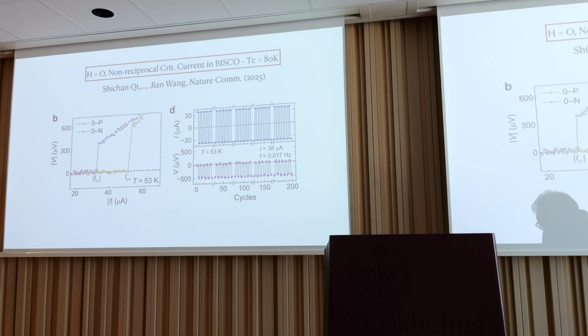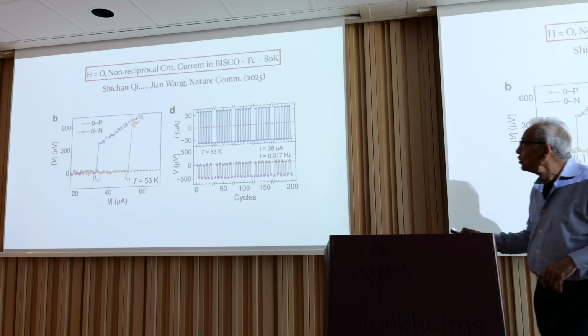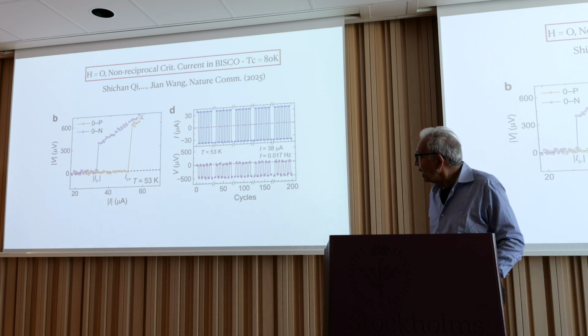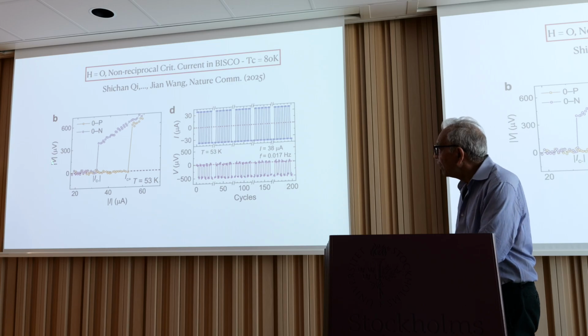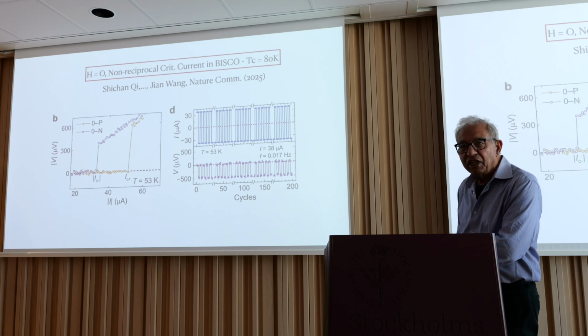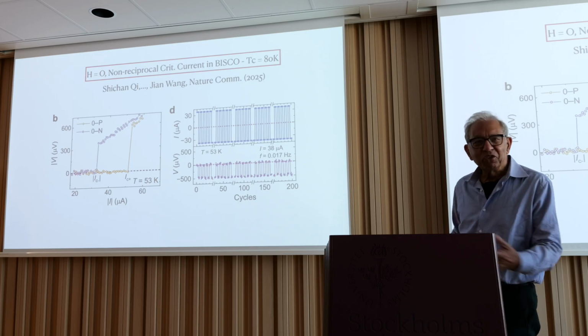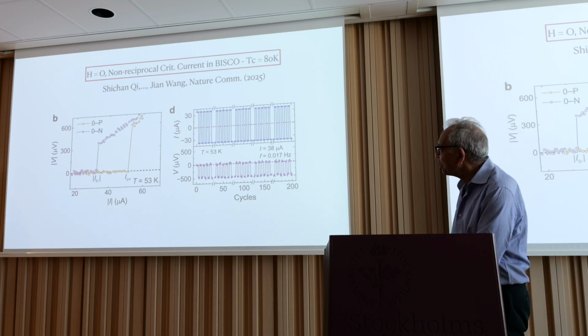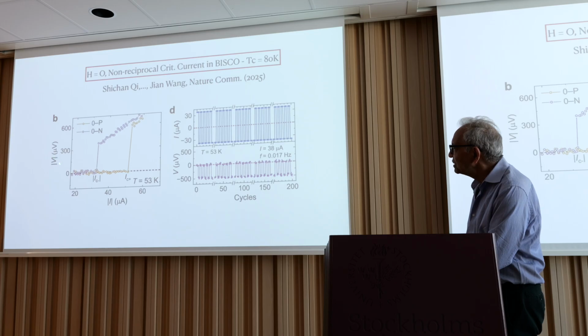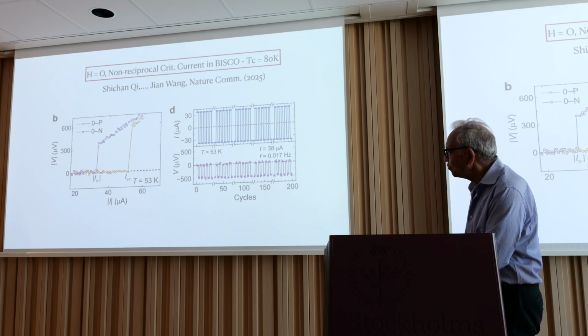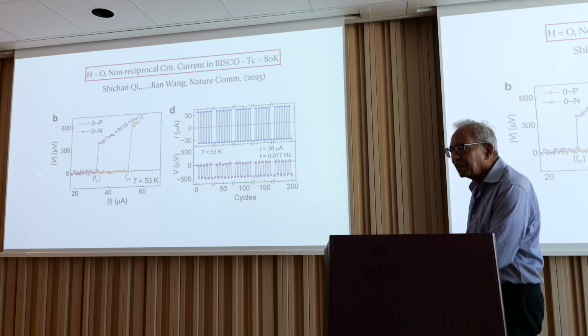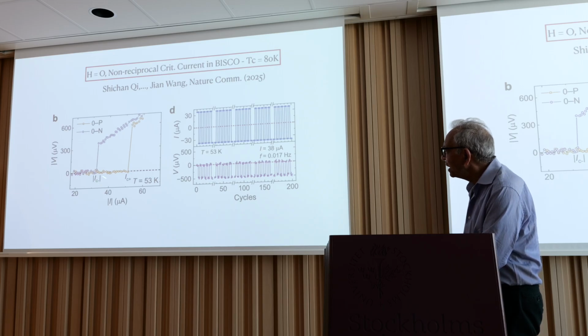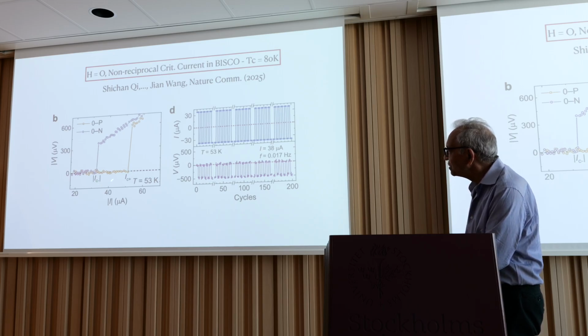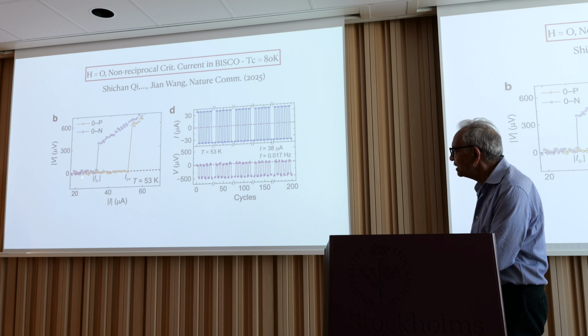So here is the data in the cuprate, and Dr. Wang does not plot the dV/dI derivative, which would look much more impressive. He plots the voltage developed as a function of current, and this is current in one direction. He has nicely put a modulus here, and then he applies the current in the other direction, and you see